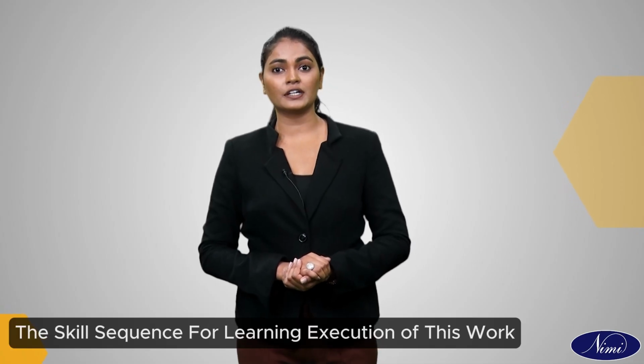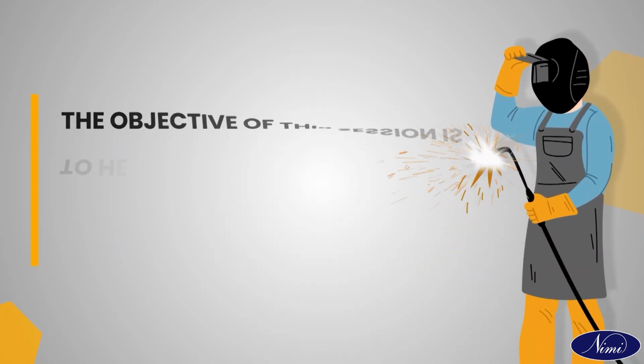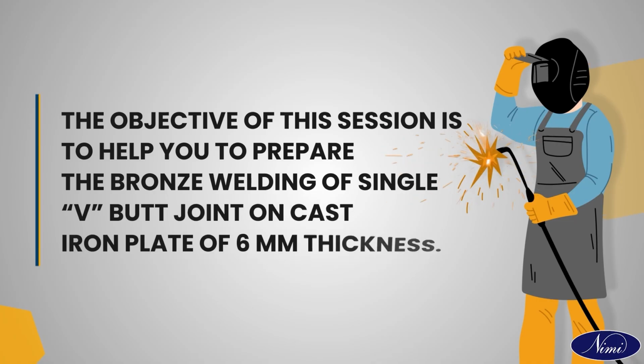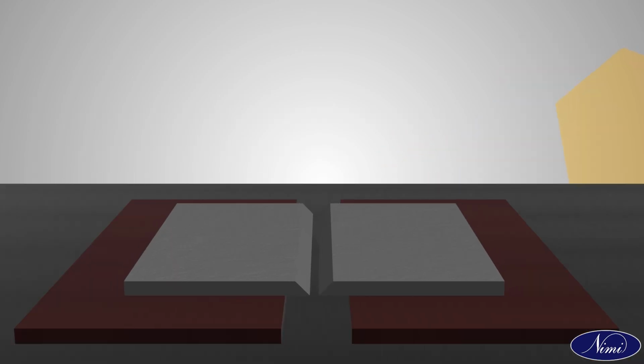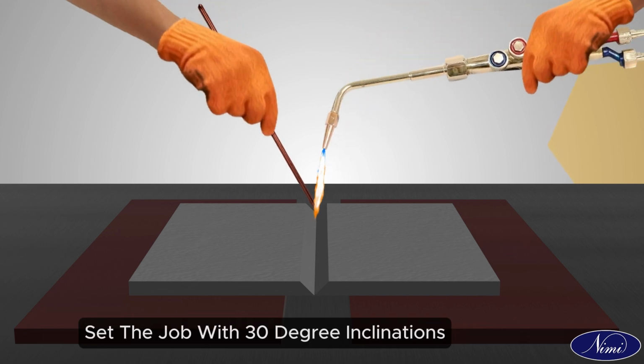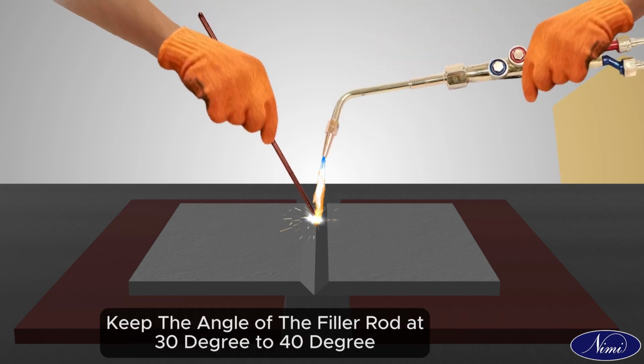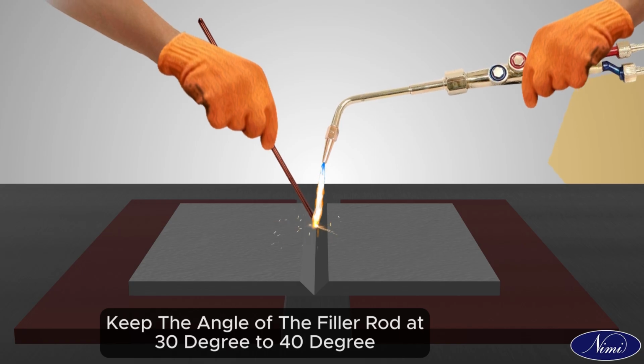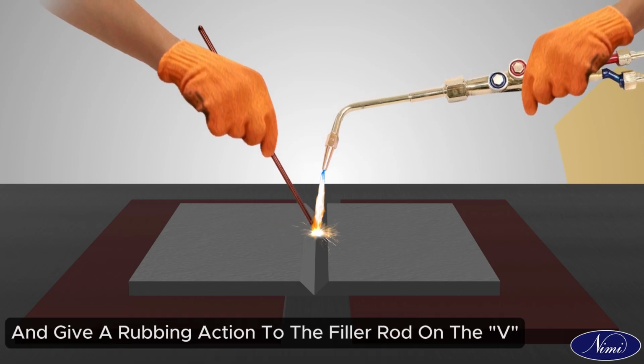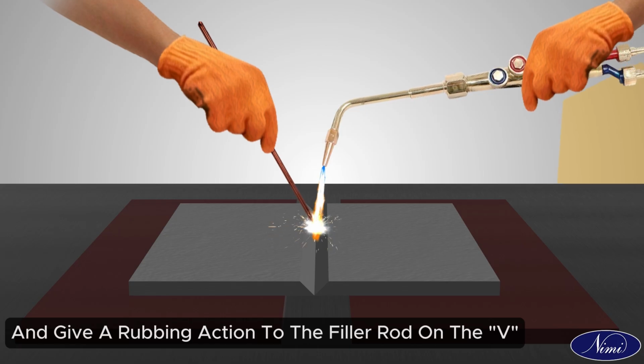Dear students, let's study the skill sequence for learning execution of this work. The objective of this session is to help you prepare the bronze welding of single V butt joint on cast iron plate of 6 mm thickness. Set the job with 30-degree inclination. Keep the angle of the filler rod at 30 to 40 degrees and give a rubbing action to the filler rod on the V.